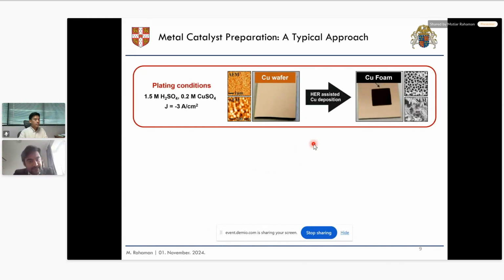This is a unique electrochemical deposition process that allows us to get a well-defined microstructure, macroporous dendritic structured copper on the electrode surface. How does it work? If we see here, it's a flat surface. We can use it as a substrate, and then we use a copper precursor, copper sulfate, in a highly acidic medium, and we apply very high cathodic current density. So we generate hydrogen bubbles because we have a highly acidic medium, and copper 2+ gets deposited on the surface as copper 0. So we get metallic copper, and the hydrogen bubbles act as a template to get this macrostructured copper catalyst.